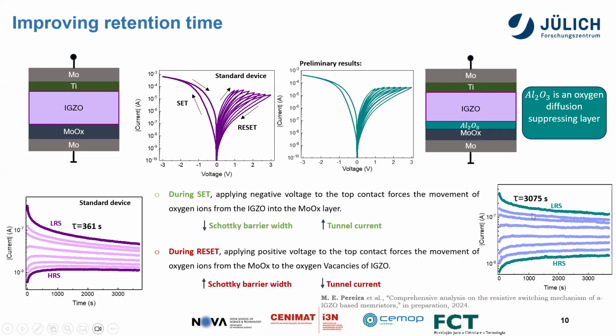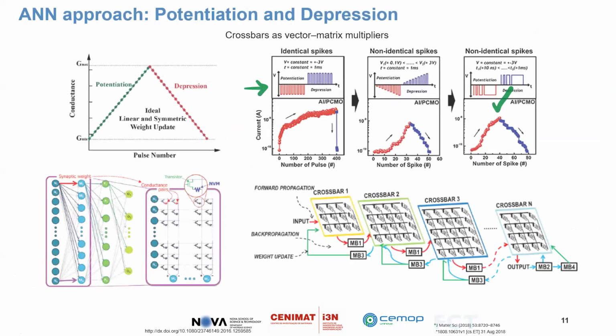It is still ongoing because of the quality of aluminum oxide, how it is deposited, and then also it should be very, very thin. So now we are testing between two centers. This is ongoing work, testing this layer and further improving the device. When the aluminum oxide is 2 nanometer, you still keep this area-dependent resistive switching phenomenon. However, when it is slightly thicker, like 3 nanometer, then you start to have abrupt resistive switching because aluminum oxide is insulating and you need to break it via forming.